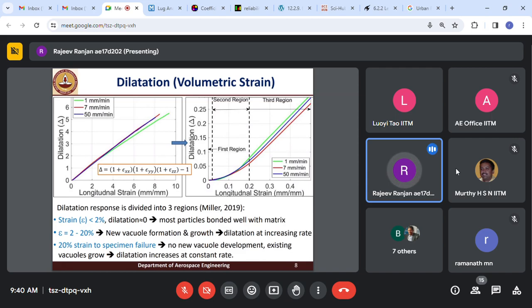In the third region, we observed that the dilatation was increasing at a constant rate with strain, and this is because after a certain strain, for this material around 20%, there is no new vacuole formation, and only the existing vacuoles are growing in size, leading to an increase of dilatation at a constant rate.